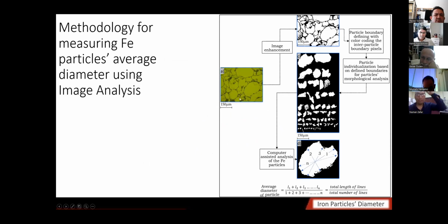But if you see the image, you see that some particles are really big and others are small. You must find a way, if you are actually claiming that you have done a quantitative analysis of the particles. When you say particles, which particles? Probably iron particles. Only the iron particles. I'm discussing only the iron particles because there is nothing I can do about the B4C particles. They are very hard and they have little influence. They don't change their shapes.